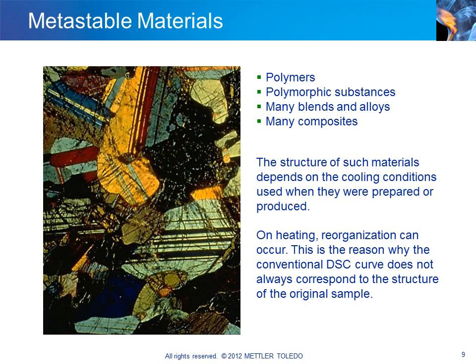Reorganization can occur on heating. This means that the crystallites melt and at the same time recrystallize to form more stable structures. The DSC melting curve therefore shows the result of the reorganization and not the melting of the original crystallites. The degree of reorganization depends on the heating rate.